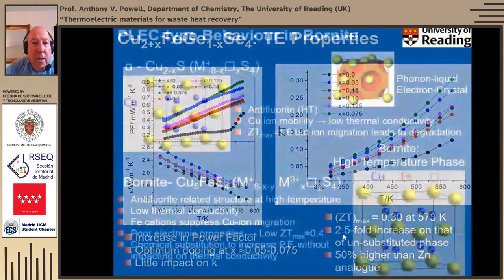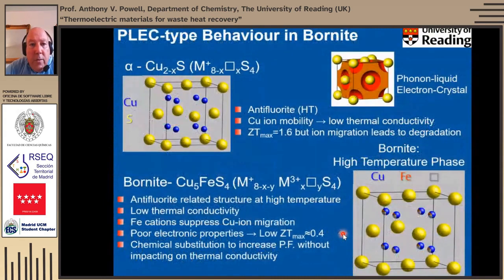So to finish, I just have a few slides on that phonon-liquid electron-crystal type behavior. The archetypal examples in many ways are the copper sulfide and copper selenide of this type, which at high temperatures are anti-fluorite type structures. And it's found that the copper ion mobility at high temperatures leads to a melting of the copper sublattice. So effectively, the anion lattice stays the same. The copper sublattice melts, and it assumes a liquid-like state. And that impacts substantially on the thermal conductivity and reduces it quite markedly. And ZT maximum reaches about 1.6.